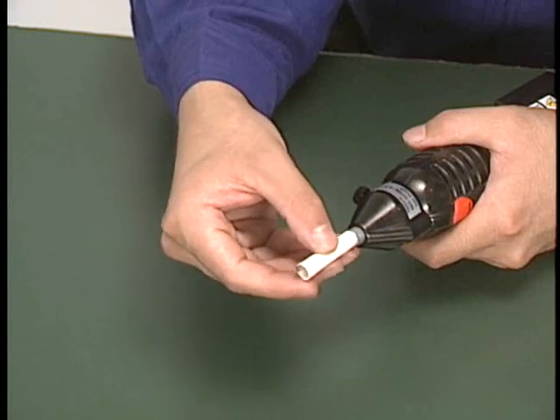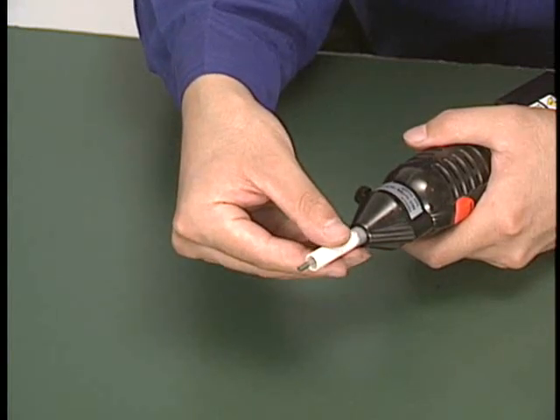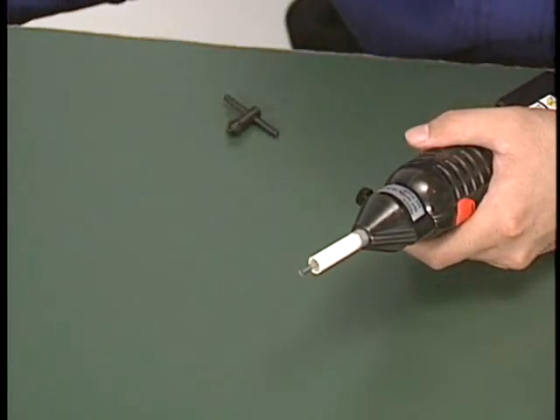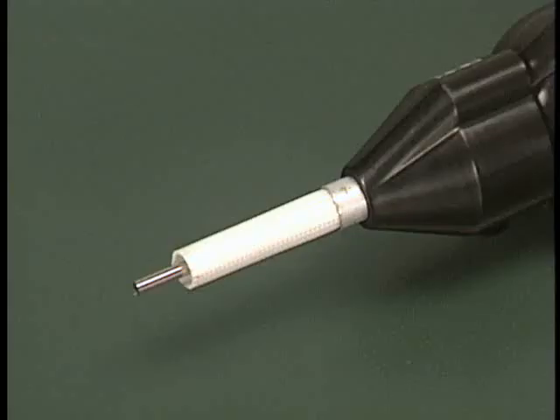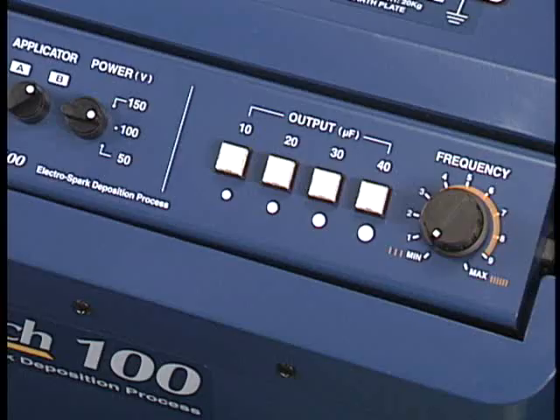The electrode should extend no more than 20 millimeters from the tip of the protective cover or shield tube. The effective gas shield is compromised when the electrode extends more than 20 millimeters from the tip. Select the best variables for the optimum coating efficiency and quality.